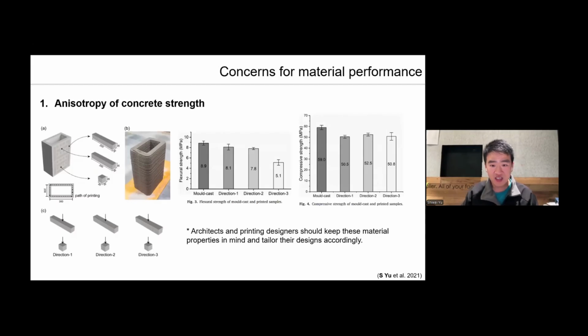One of the key concerns for the material performance is that 3D printed concrete is anisotropic in strength, which means the strength is different in different directions. This result comes from the period when I did my PhD at Swinburne Uni. As you can see from this graph, printed structures show different strengths in different directions. The most obvious example is direction 3, as you can see here.